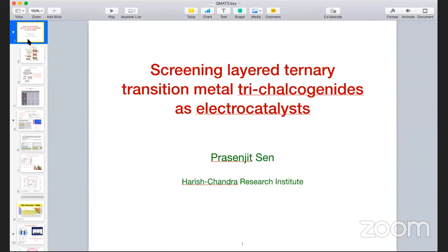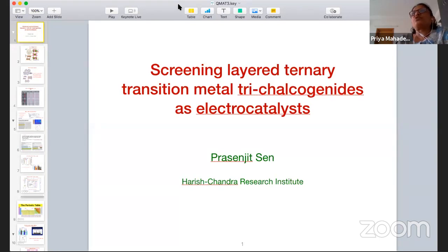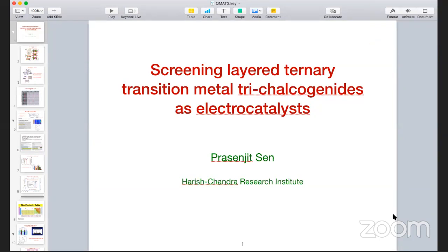What I'm saying is the 13 compounds that seem to have the best delta GH values have not been reported in these layered structures in the ICSD. I can't recall offhand if some of them exist in more three-dimensional structures, but definitely not in the layered structure. Because if there was a three-dimensional analog, then usually the rule of thumb is that you explore the other polymorphs of the same substance and see whether it falls within, some experimentalists quote 0.5 eV or something, because if the energy differences between them are very large, they may never form. So I was just wondering whether you had such numbers for these compounds.